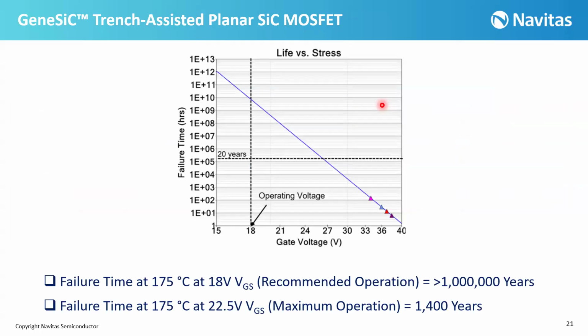Here are the TDDB results. We are considering the lifetime of our gate oxide by applying a high voltage, 8 megavolt per centimeter, 9 megavolt per centimeter, and so on, in order to find out the lifetime at the recommended operation. If you look at this picture, it shows that the failure time for 18 volt, which is the recommended operation, is more than 1 million years. And the failure time at 175 degrees C at the maximum operation, which is 22.5 volt, is more than 1400 years, which is obviously higher than the lifetime that we need.